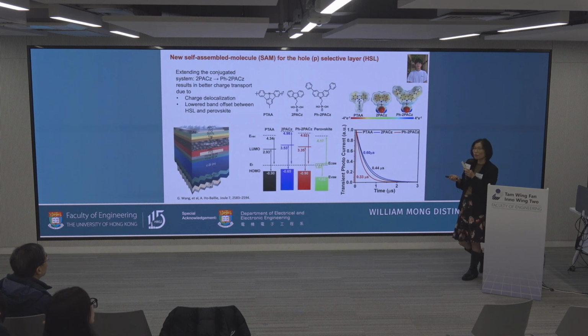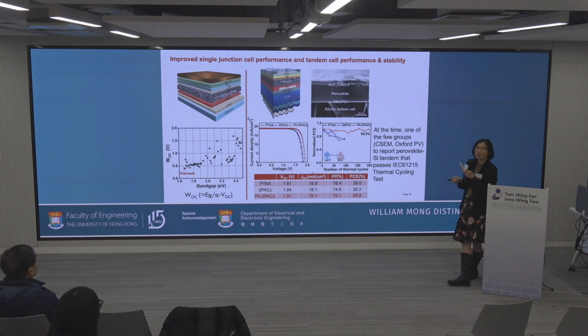And the other beautiful thing about PIN is people have been looking at using self-assembled monolayers to engineer the functionality of these layers for hole transport. So Guoliang is the very first student in our group who worked on engineering the hole transport layer. In this case, he added the benzene rings there to delocalize the charges, and through that he could move the LUMO and the HOMO levels of the hole transport layer, and therefore improve the charge extraction. Also, the material is thermally stable and it improves the wettability of the perovskite layer. So the perovskite layer is happy, and therefore there are fewer defects and a much better interface. And through that, he was able to reduce the voltage loss in this